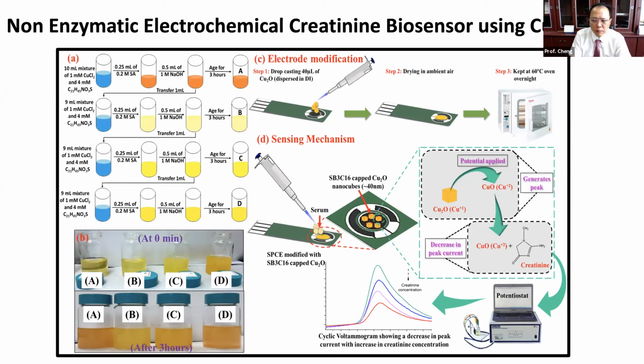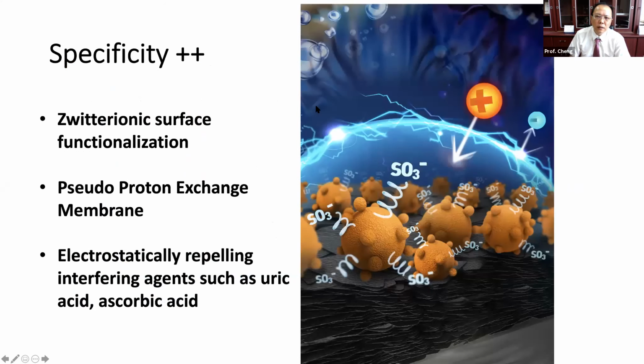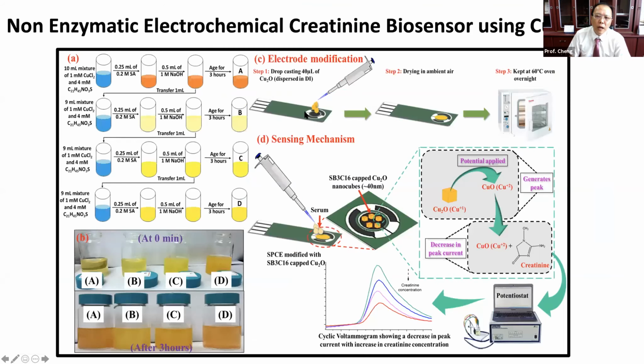In our research, we try to use metal oxide. We use copper oxide, Cu2O, this kind of nanoparticle, and we use a stepwise synthesis method. You can see the different steps, and the size and the morphology are different. We will just drop this copper oxide onto the carbon electrode biosensor. Then we can do the creatinine sensing.